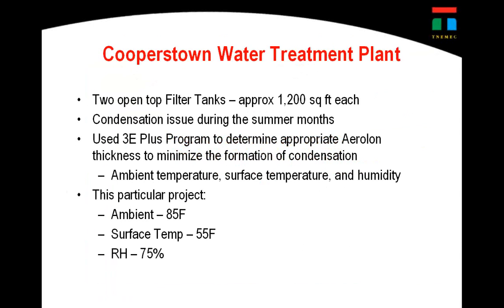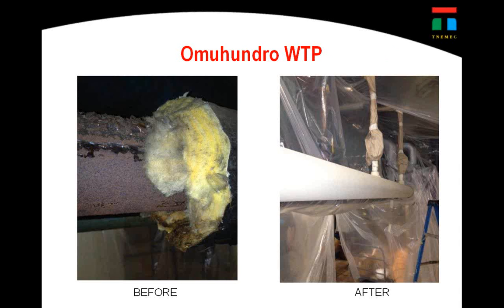Okay, so what we also looked at, well, this is a couple of projects that we've actually completed. This is in Cooperstown water treatment plant. And this is a very big problem in the water business. They have open-top filter tanks, 1,200 square feet, with condensation issues in the summer months, and you get cold water coming in from either the ground or from a lake. Deep lake, you get a lot of sweating that takes place. So we had an ambient condition of 85 degrees, surface temperature 55, and RH of 75. And what they were constantly having was this.